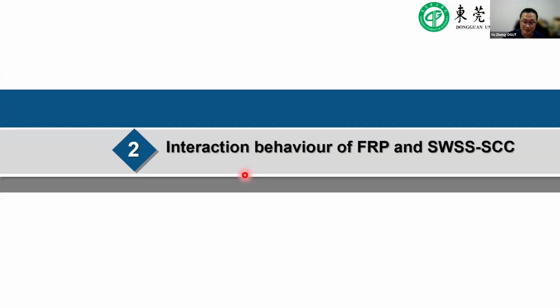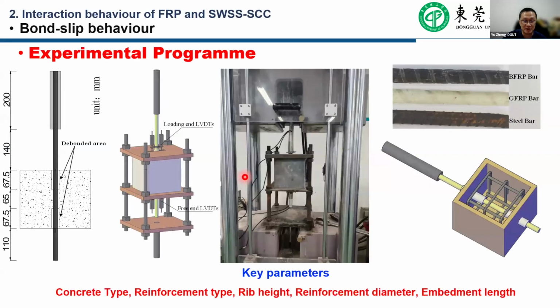The second part of this presentation is where we try to introduce the study of the bond behavior, the tension stiffening behavior of the FRP reinforced SWSS-SCC. In the first stage of the study, we used the pull-out test to study the bond behavior between the reinforcing material and the concrete. Additionally, we also used the AE method, the acoustic emission method, and piezoceramic as the transducer to identify the damage process of the whole